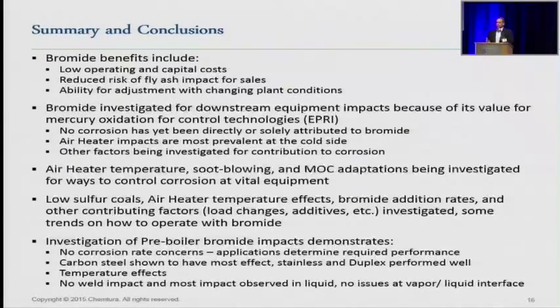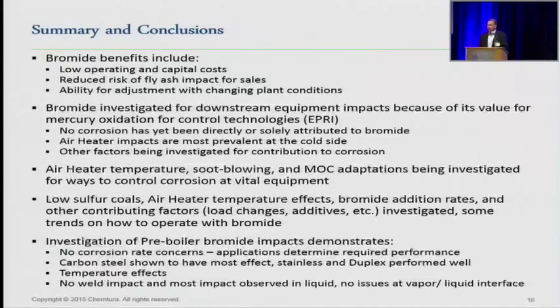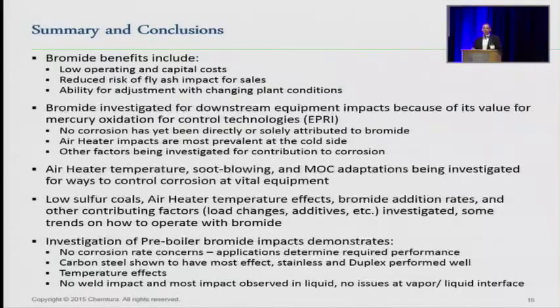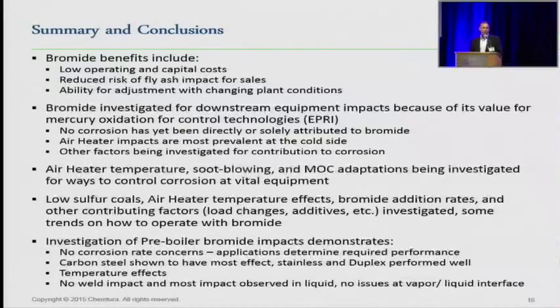The air heater temperatures, again, they did mention in their report that using some different soot blowing tactics were good when they were using carbon to avoid having solids build up on the metal surfaces, and where you have the ability to trap condensed acids, that's shown some benefits. And then the low sulfur coals, air heater temperatures, making sure, I guess that's the other thing too, if you are using bromide, keep a good watch on what you're doing in your system, what your temperatures are. Again, maybe years ago that was less of an issue because you were running that thing full out and you didn't have those ups and downs. When you do have those temperature changes now, you're going to run into a big issue if you start condensing acid out.